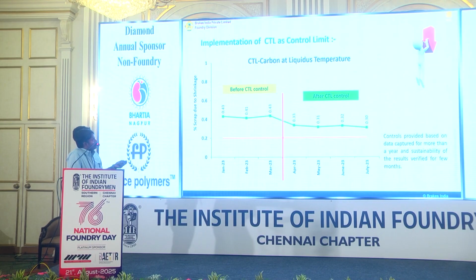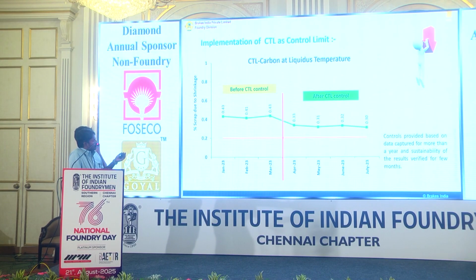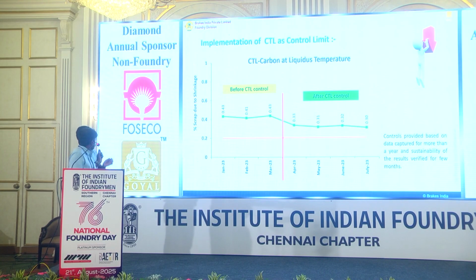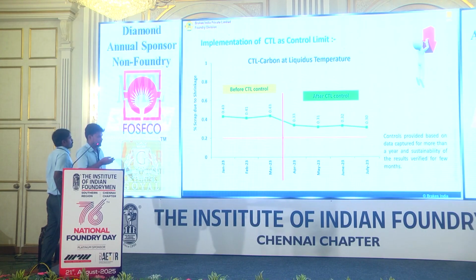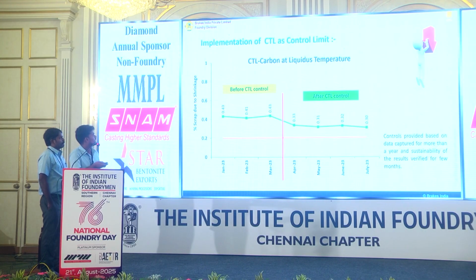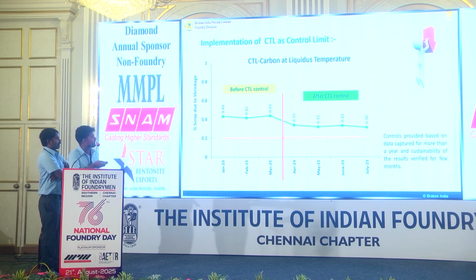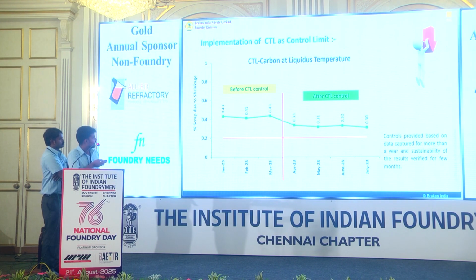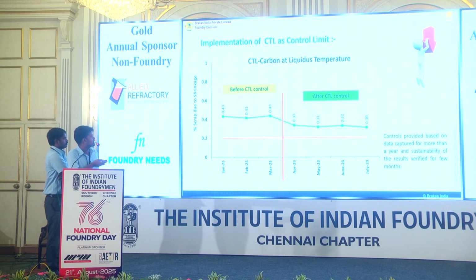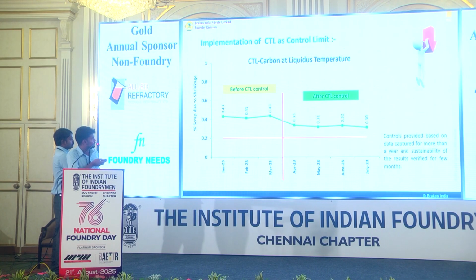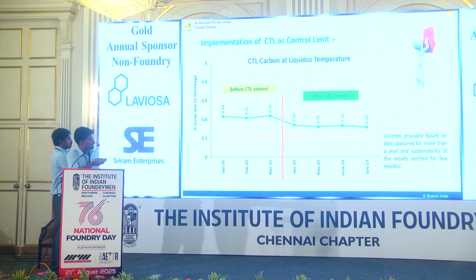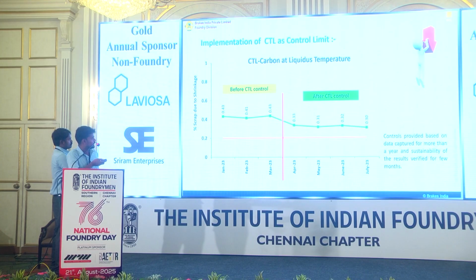So these are the achievements after implementing these parameters. From the thermal analysis, we gave a control for CTL, carbon at liquidus temperature. First, we gave the CTL control. After implementing this CTL control, we drastically reduced the scrap due to sinkage. Before that it was 0.43%, now we have achieved 0.30%. Approximately 30% rejection has been reduced.